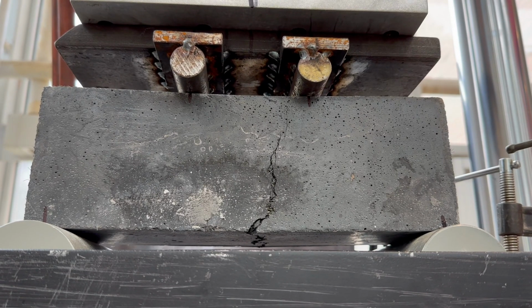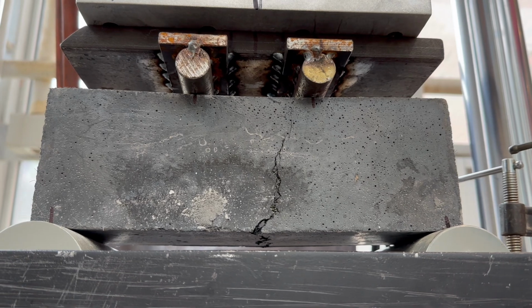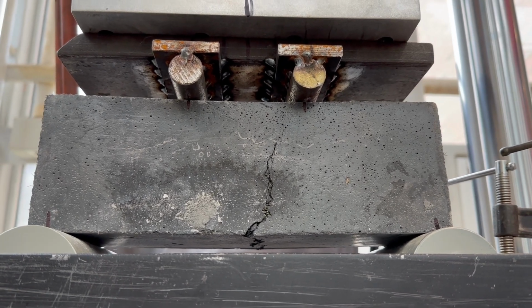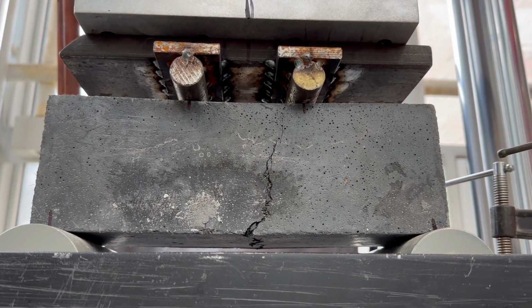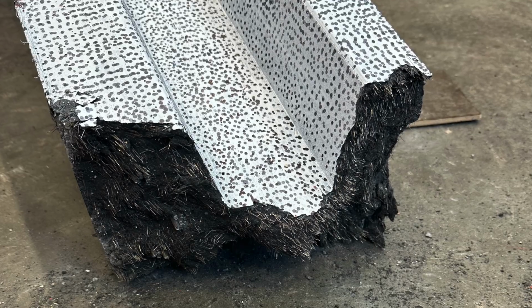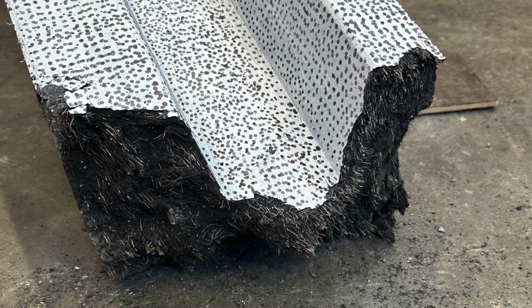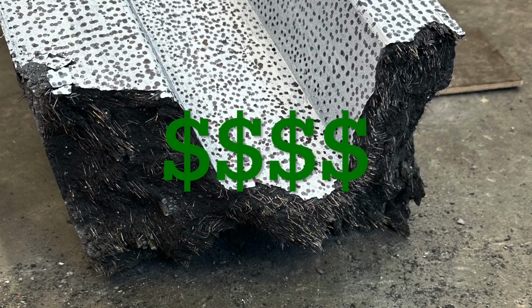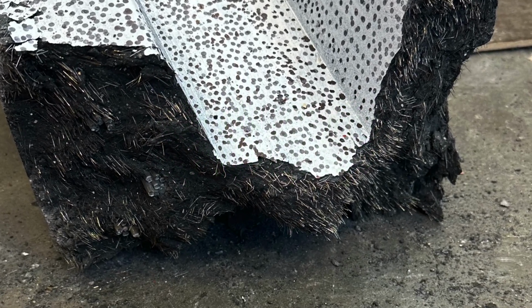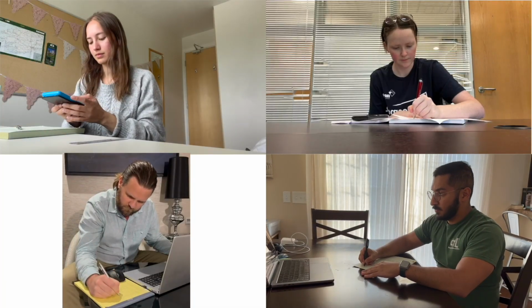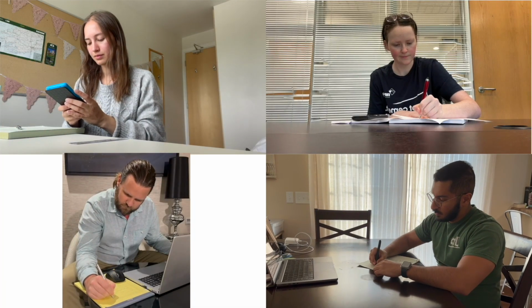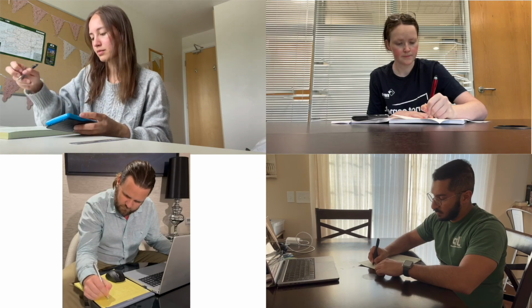It's also known for its superior tensile capacity, thanks to steel fibers that are well distributed throughout the concrete mixture. However, this material is, of course, a lot more expensive than traditional concrete, so it was important that our design was as structurally efficient as possible. To come up with our design, we used a mixture of hand calculations and finite element modeling to iterate on optimizing the geometry.